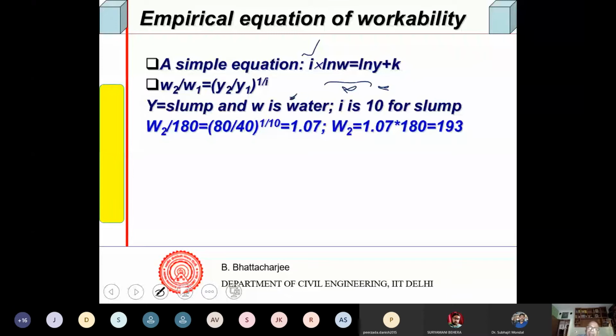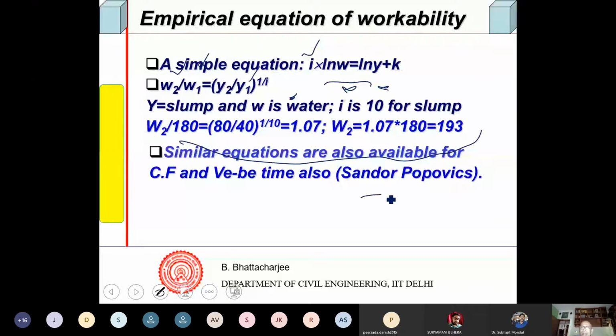So from this, one can find out if W2 is the water required for a slump value of Y2, then W1 is the water required for a slump value of Y1, or vice versa. So you know one and the corresponding slump, and your required slump is known, you can find out the water demand. That's the kind of relationship. It is the simplest of all. There are many such similar ones. Sandor Popovics' book, Quantitative Methods in Concrete Technology, Volume 1, gives you 50 plus equations, some for paste, many for concrete, and none of them are the same. They don't give the same result, because they're all empirical, done by tests, done by different people at different places, in different conditions. So not based on theory.